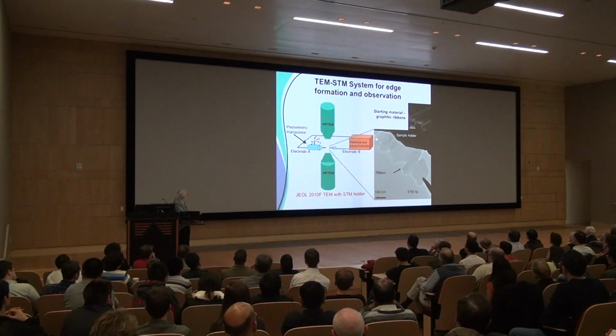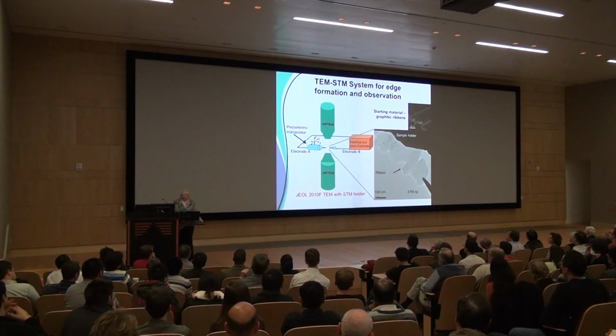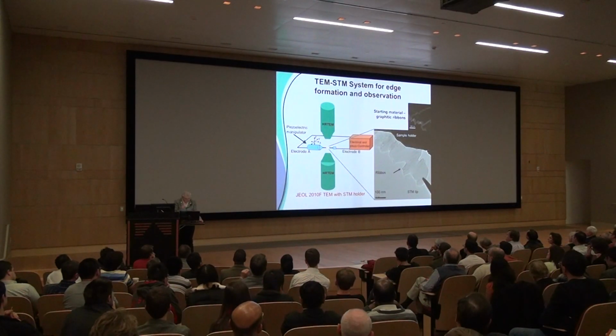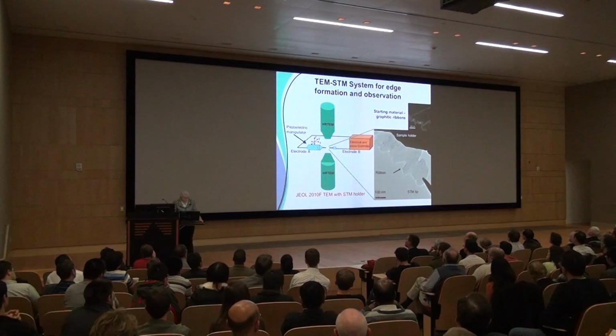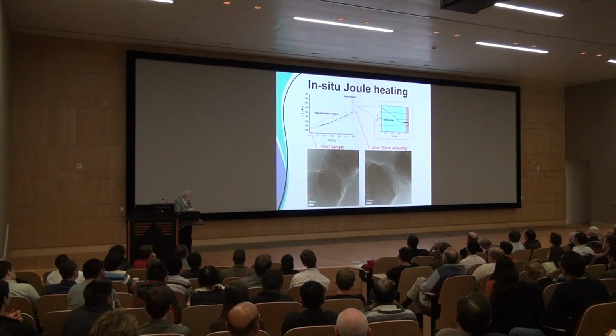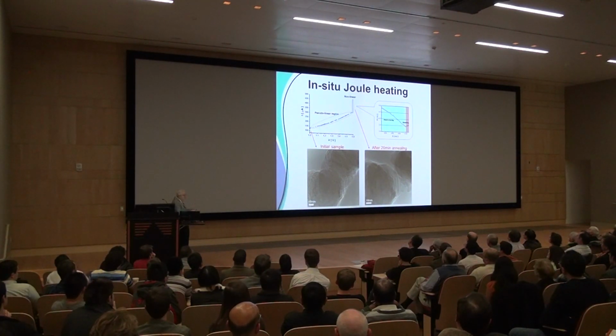So put a voltage across here, and you get a current. And we send the current through the ribbon, and the ribbon looks like this. The ribbon is sort of a messy little thing, and it has about 20 layers of graphene. It's not a single layer. It has a few layers. And that was made by another student, not the student that did this. So you start out, the IV characteristic starts out linear, and then you get above 1 volt applied. 1 volt isn't very high. It gets nonlinear, more and more nonlinear, and then it just shoots up like crazy here.